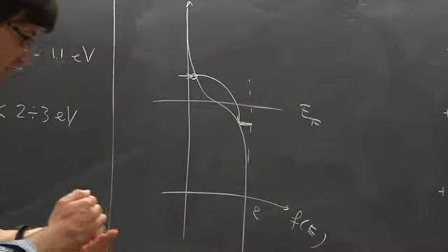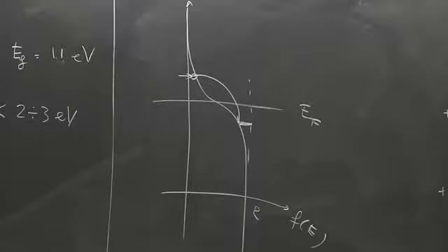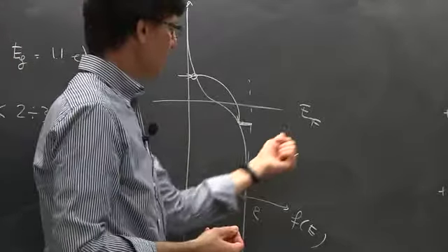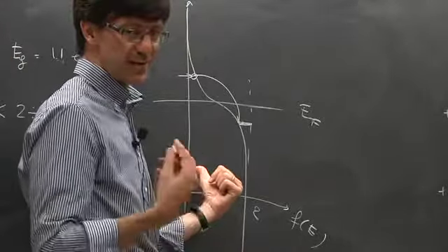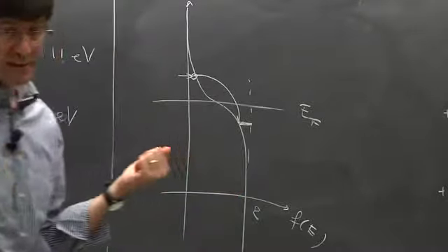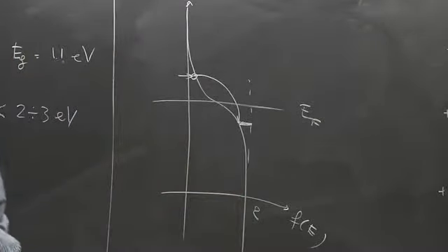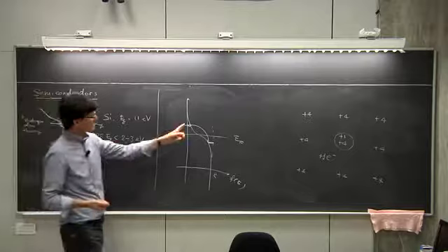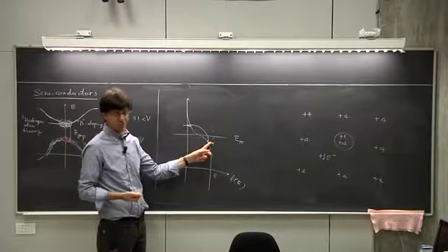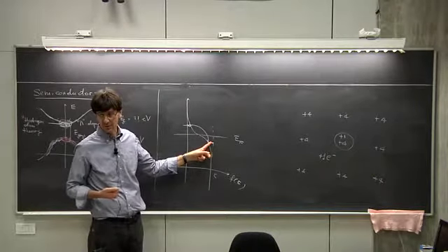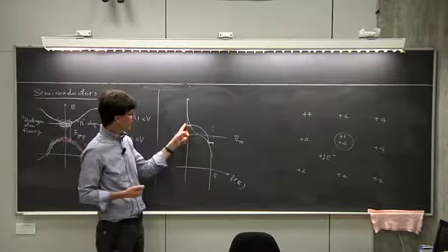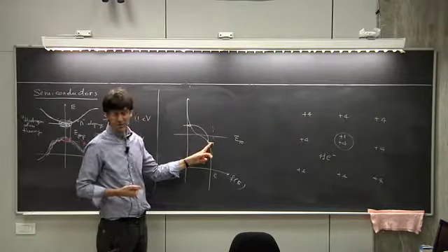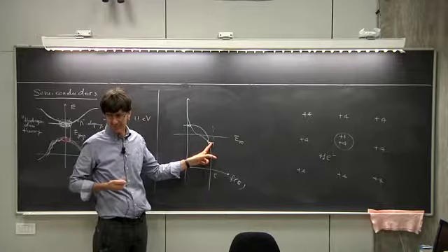Okay. The answer to this question is that you shouldn't consider energy at finite temperature as the relevant variable that needs to be minimized. It's the free energy of your system that needs to be minimized. Okay? So that includes entropy as well. The reason why the electron doesn't go from here to here is because it would lose a lot of entropy in going from here to here. You can show that if you take an electron from here to here, you're actually increasing the free energy.